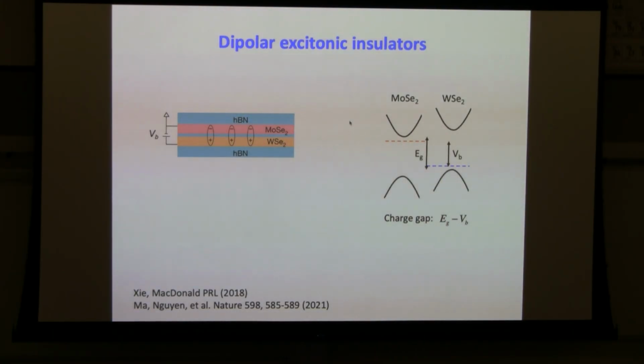To create this dipolar excitonic insulator, what we do here is that we put two layers of materials on top of each other with an insulating barrier in between. For instance, we put the moly selenide and the tungsten selenide with a thin layer of hexagonal boron nitride, which is an insulator, separating the two layers. And we can apply a bias voltage VB between these two layers.